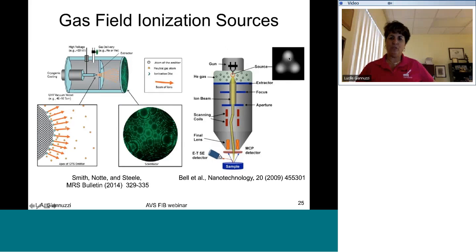And what you wind up doing is getting these small little beamlets of helium sources. The idea then is you sharpen the tip to where you get sort of this trimer at the source. What's not shown here is that you do get some smaller emission from back around here, but that's not critical. The idea is that you get this trimer of sources. So these 3 atoms which are sticking out from the tip are basically your source of helium ions.